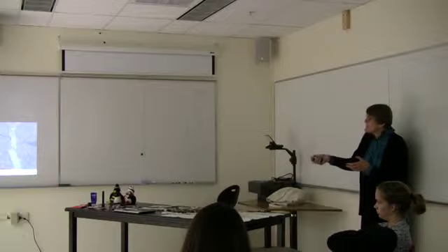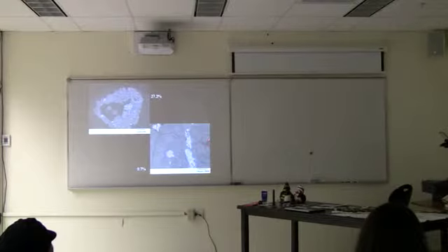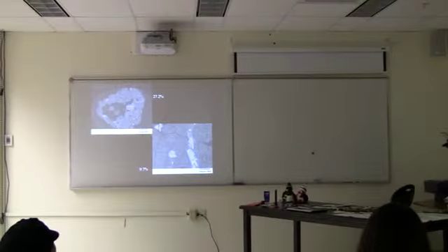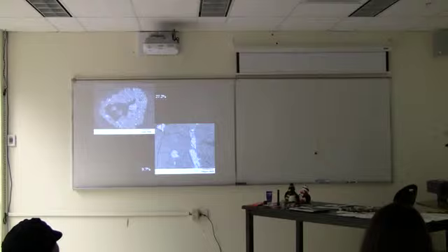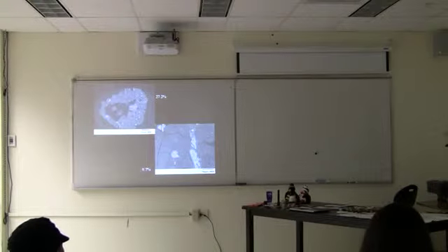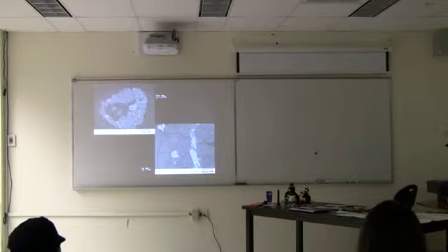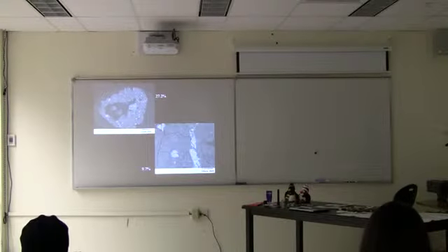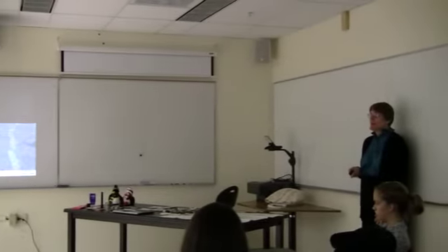Now I've learned that you have to go back and take these big maps of the whole thing, and then I have to correlate where this picture is on this section and say, oh, that's the tail end of one of these big voids. I need to count it. And so I need to go back and redo some of my carbonaceous chondrites, not only at higher magnification, but also at lower magnification, to see if I can find more of these voids. And then, of course, what I was doing here is trying to approach it from the other direction.